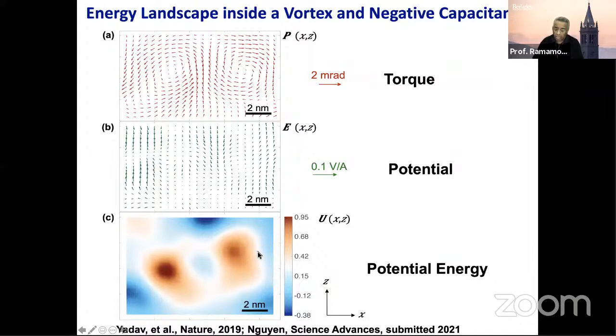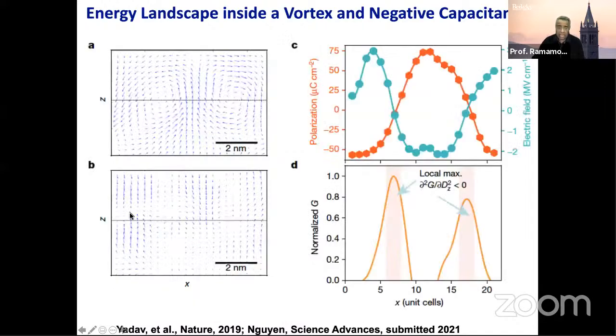Okay, and therefore, what this told us was that indeed, in these vortices, you have regions where the energy landscape, if you can reconstruct it, looks like this right at the center of the vortex. And therefore, we have indeed trapped negative permittivity in a material right at the center of the vortex. And this business of negative permittivity is a very exciting, controversial topic in condensed matter, at least in polar systems. And this was one of the first direct measurements of the existence of the negative permittivity state.